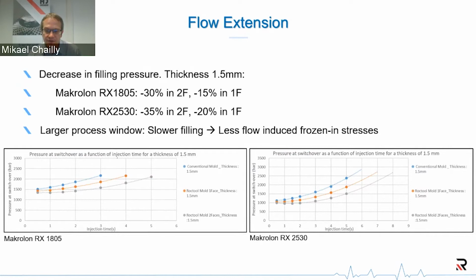On this one, we have considered the same disc, but now with a thickness of 1.5 millimeters. This time, whatever configuration, we managed to fill in the part. But you can observe that as we have increased the thickness, we come to the second part of the U curve that Vito mentioned, that was on the right side. So we see that you can increase.